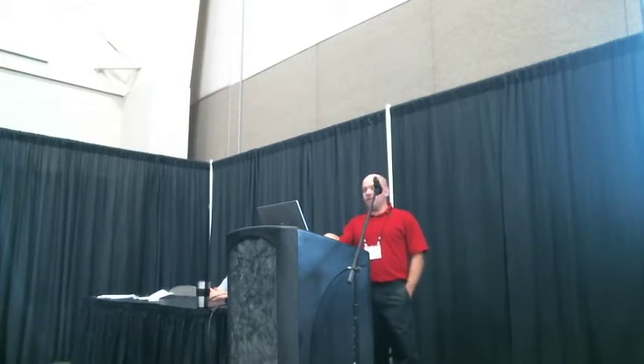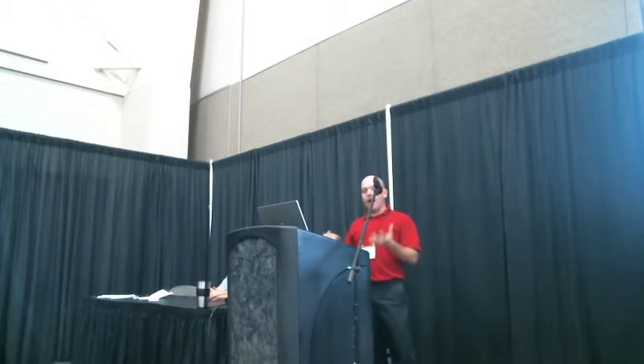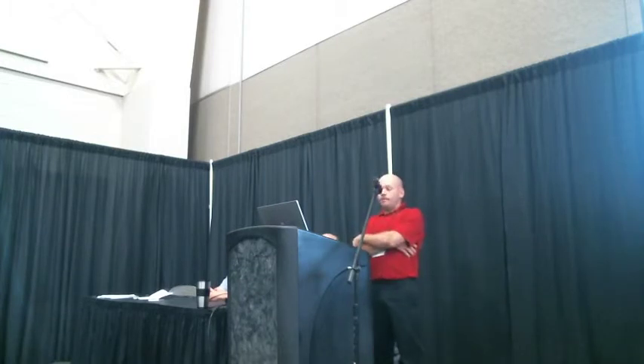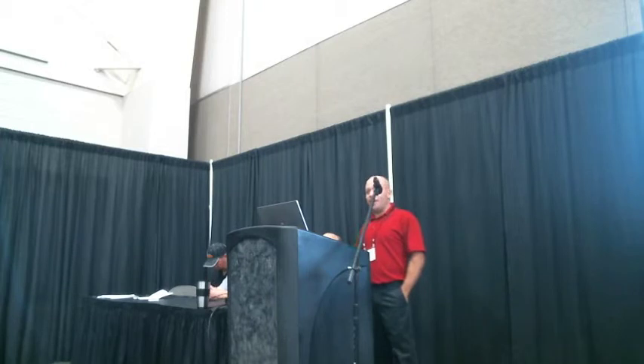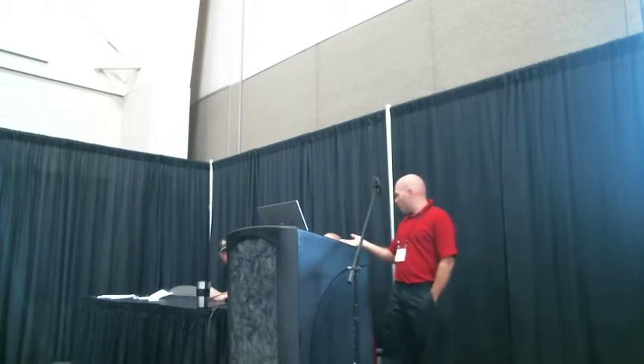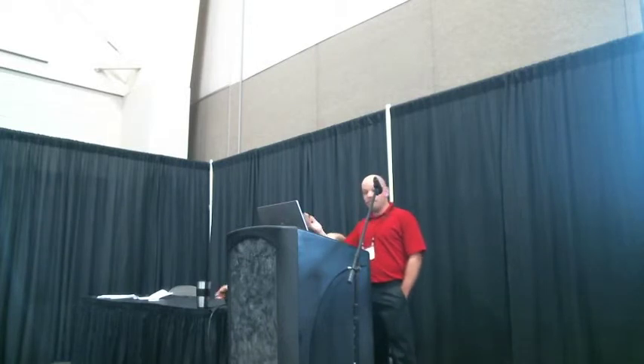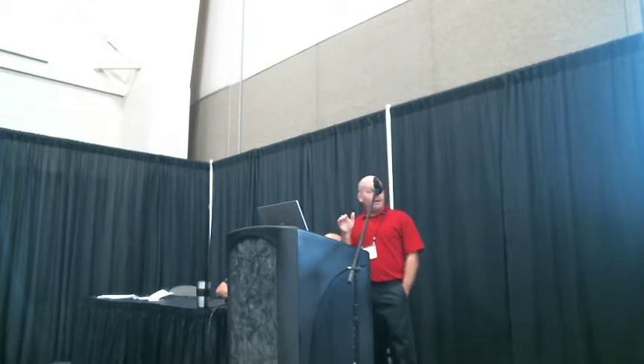And then the next piece is, now how do I, so that's the testing piece. Now how do I control this material to make sure I'm getting a consistent process? So really I left it up to the contractor and said, I just need a material that is 2-inch minus. Just don't leave me big pieces in there. And I didn't even put any acceptance testing on that 2-inch minus. Just told the field guys out in the crew here, hey, just every once in a while, take a 2-inch sieve, grab some of the material, run that over the 2-inch sieve, and make sure it all goes through there. And if you do that, then they're consistent. And I don't know how often they did that. Once every day, type time frame. And then I also put on the materials the requirement of the prime coat to go on top of it.